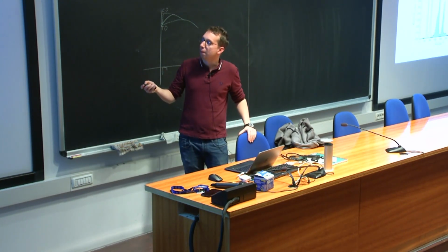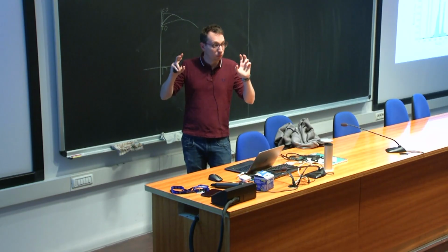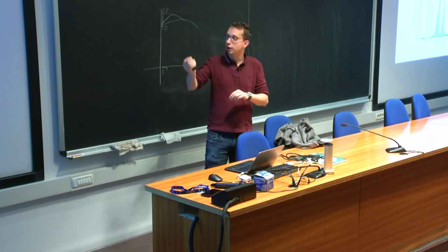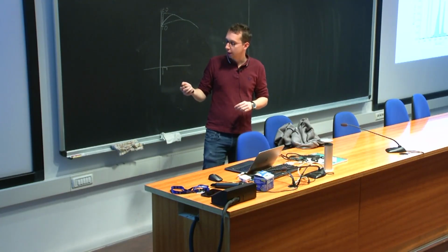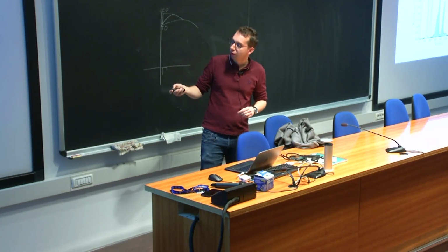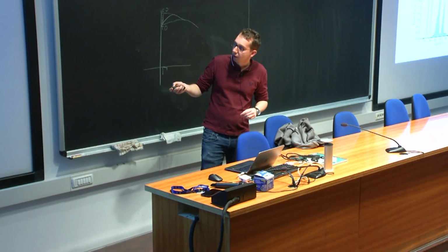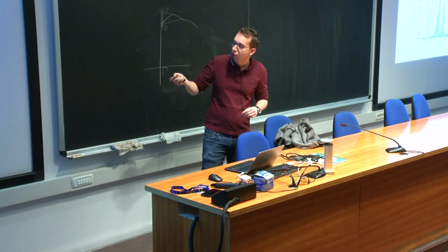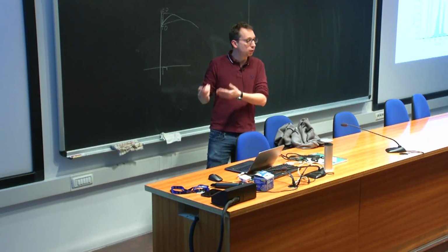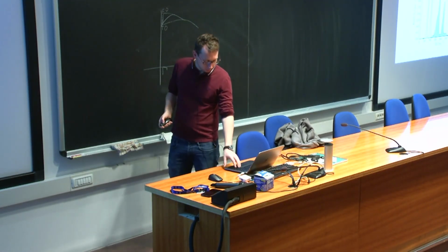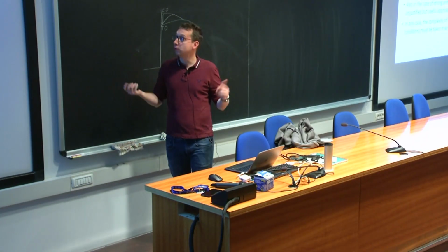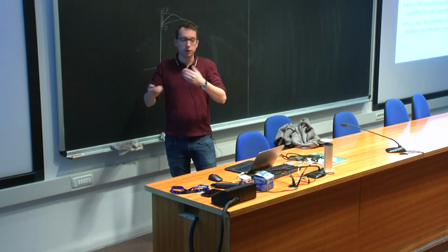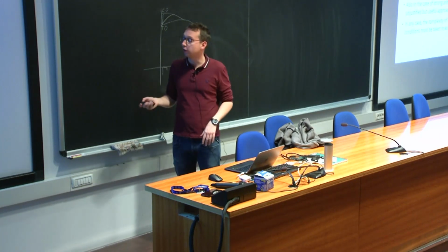But these modes which are associated with the hydrogen going a bit freely around between the palladium atoms have some interesting features. It is not symmetric. It has satellite peaks. And if you compare it to just a superposition of line widths, which is the red curve, you can see it is quite different. So it is possible in principle to combine the cross-section of Raman or infrared with this kind of calculation. As far as I know, nobody's done that.